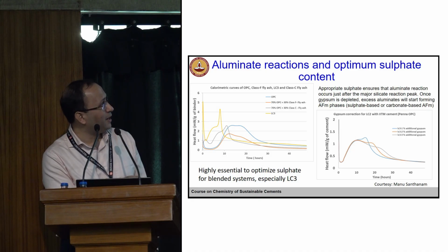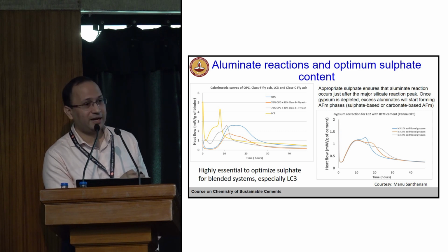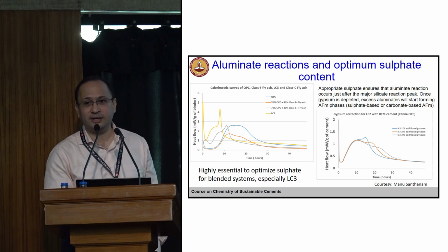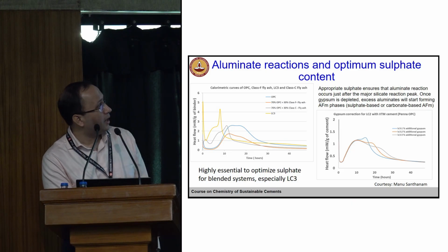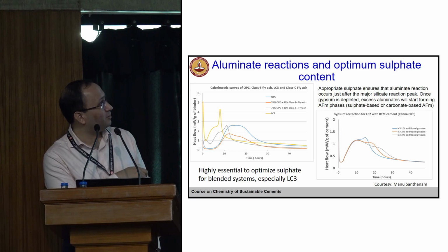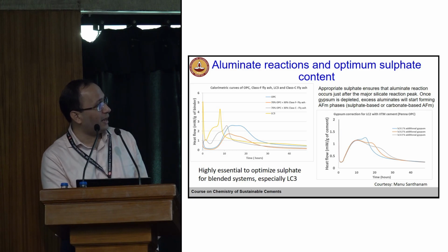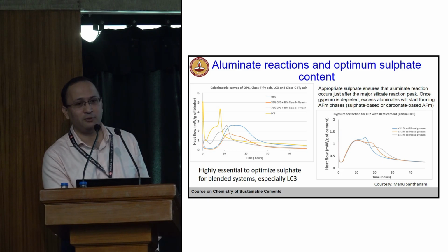Now, depending on the type of fly ash, this was class F fly ash, in this case class C fly ash, it also accelerated. It reduced the induction period, right? That could be because of the calcium content, could be because of other reasons also. And the LC3, for an example, you see here, right? So you see this needs to be balanced. So now what happens when we add extra gypsum, additional gypsum, right? You see the shifting of this peak. So that will ensure that this is not basically interfering with the silicate hydration.